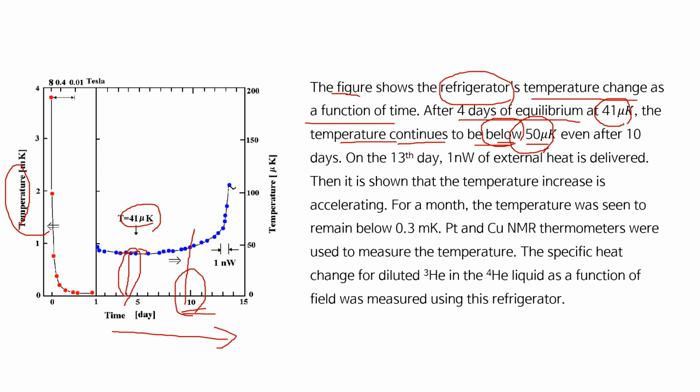On the 13th day, 1 nanowatt of external heat is delivered to the refrigerator. Then it is shown that the temperature increase is accelerating.